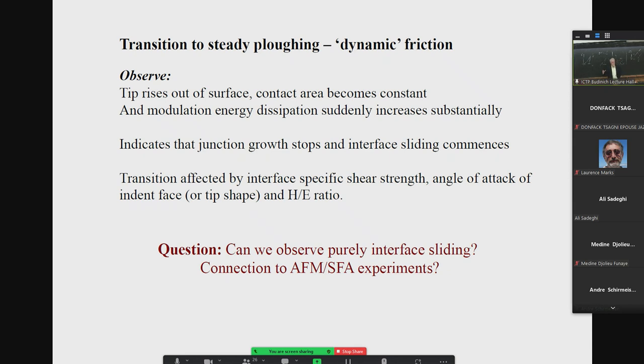It implies that even in systems which are deforming plastically, like a scratch process, it's that interfacial energy sliding which is actually the dominant process, which, from the point of view of a nanotribologist, should be mightily encouraging. Because it means even in stuff where you're causing grooves in surfaces, right, what you're measuring at that single atom and molecular scale really matters, despite the fact that it appears to be a purely plastic process. So that's very encouraging.